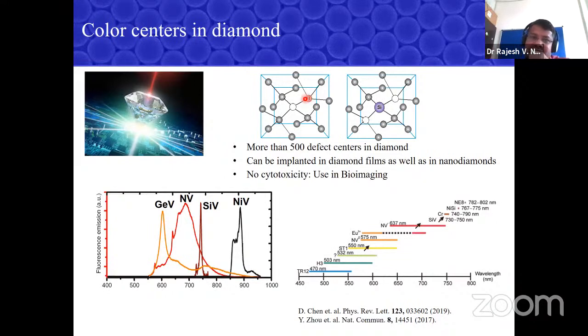And this pair is what is called a nitrogen vacancy pair. So if you have a diamond, which is a transparent material in the visible because its band gap is 5 electron volt, but diamonds look colored, and the color in diamonds comes because of these kinds of defects. If you see a diamond which has a pale yellow color, that is most probably due to the nitrogen vacancies.